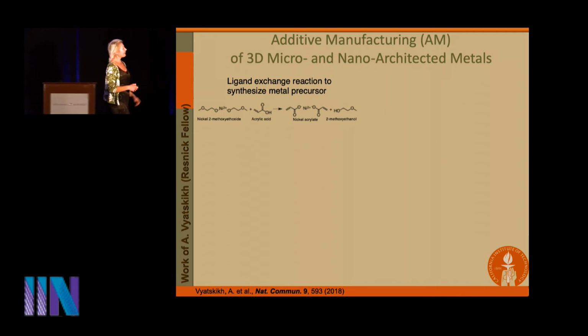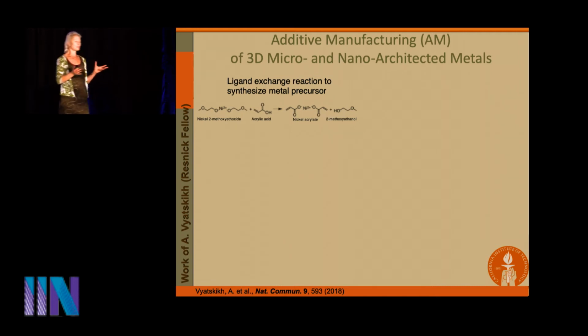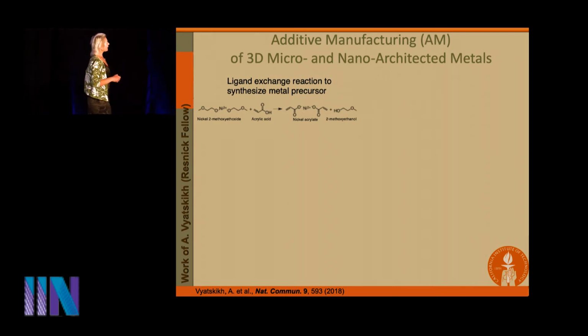All right, so we did not want to only practice our two-photon lithography 3D sculpting using IP-Dip and IP-S, which are the two commercially available resists. And so a couple of years ago, my student looked at these resists and he said, well, I want to try to make something else. In fact, I'm very interested in additive manufacturing of metals. So this is where we begin our additive manufacturing story. He looked into a ligand exchange reaction. What we mean by that is that if you have a metal ion that is trapped inside of an organic shell, you can mix it with acrylic acid and interchange it for the acrylate groups, which then become amenable to photoinitiated reactions.